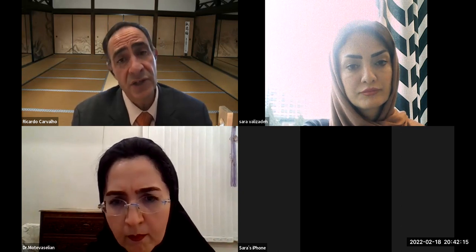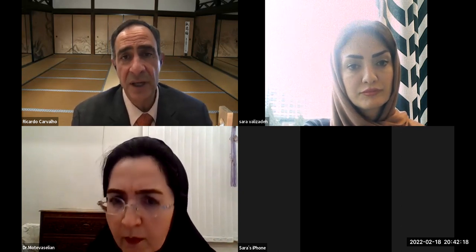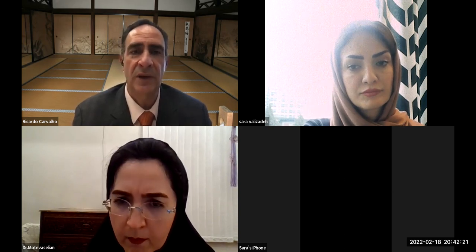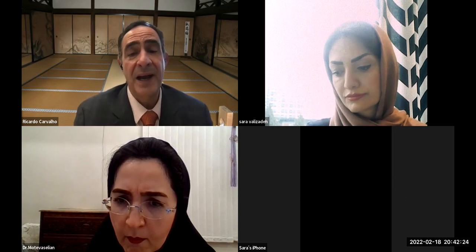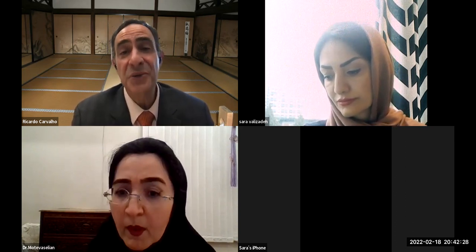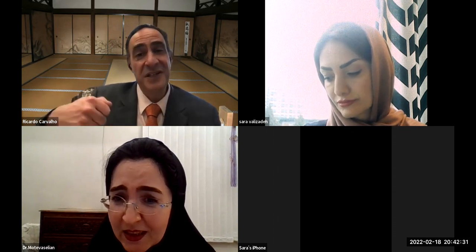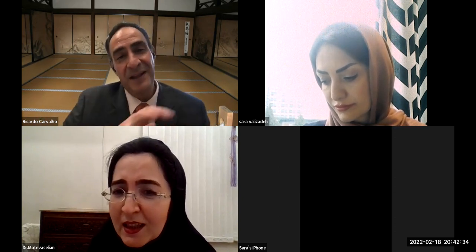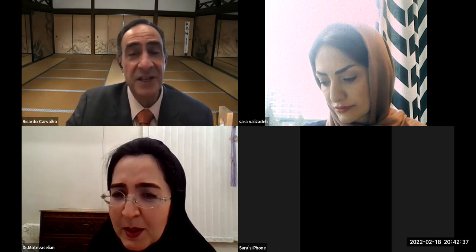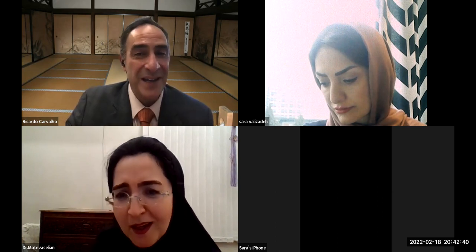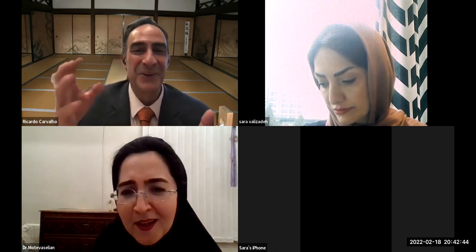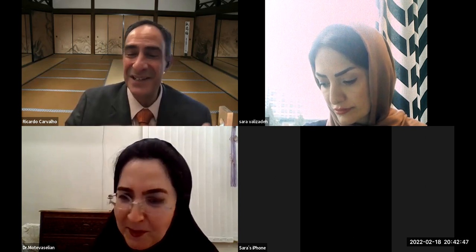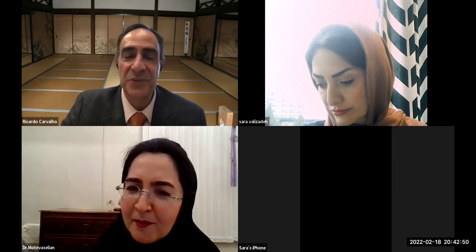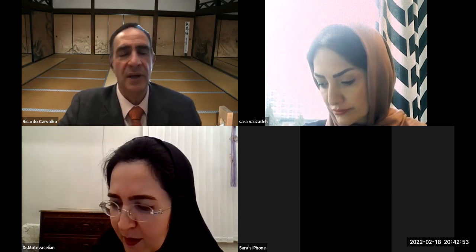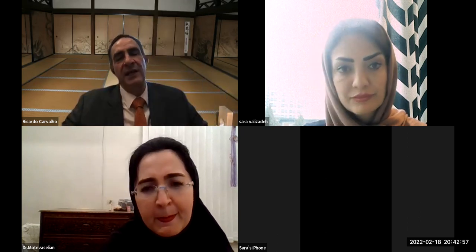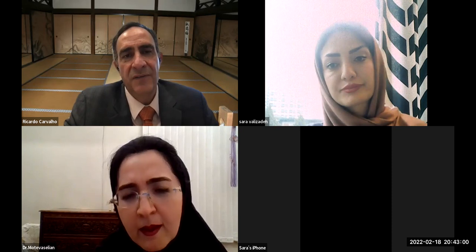some people recommend ultrasonication if you have it available for 2 minutes. That facilitates also the removal of the try-in paste. But if you apply after the silanization, it's also easy to remove by just rinsing with water, because remember, silanization leaves the surface hydrophobic. Try-in paste is usually water-based. So once you rinse, it's much easier to remove. But ultrasonication is a good way to remove any of these debris or particles from the porosity.